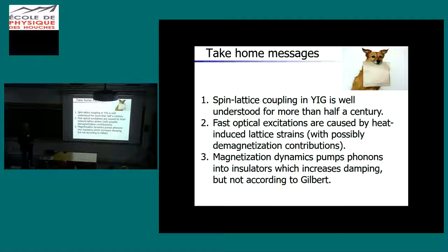So then we come already to the take-home messages. The spin-lattice coupling in YIG basically is understood for a long time, but we still find surprises and new results coming out of it. We understand that the fast optical excitations by focused lasers are caused by heat-induced lattice strains. If you have large magnetization damping, what you basically see is the phonons. You detect the phonons by the locally excited magnetization. But you also see all sorts of spin waves if you have lower damping and strongly focused laser beams. Finally, magnetization dynamics pumps phonons into insulators, and this increases the damping, but not according to the Gilbert phenomenology.